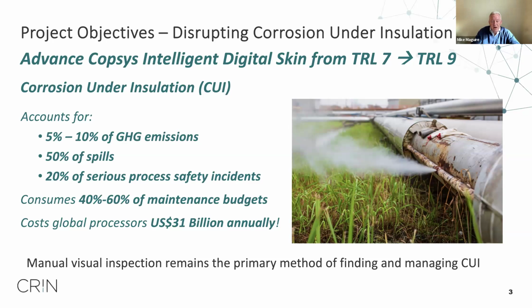Corrosion under insulation is probably the single, actually it is the single biggest corrosion problem within oil and gas production and in petrochemical and process industries in general. It accounts for 5 to 10% of greenhouse gas emissions, which we would like to eliminate. 50% of spills. It's at the root cause of about 20% of serious process safety incidents. And if anyone remembers the Piper Alpha disaster some years ago, there was a big CUI component in the breakdown of events that led to that disaster. And it consumes right now about 40 to 60% of maintenance budgets on aging process facilities, costing global processors about US $31 billion annually.